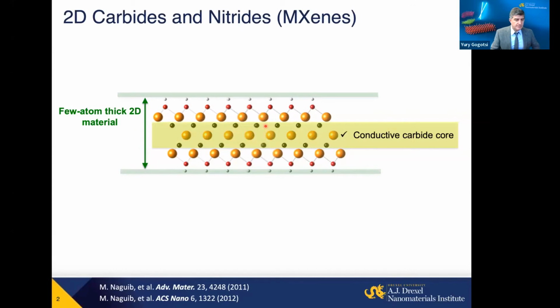What is unusual about those materials? The majority of them are metallic materials with a high density of states at the Fermi level, a high concentration of carriers. They have a conducting carbide and nitride core. But their surface looks like a surface of a transition metal oxide, hydroxide, chalcogenide, or halogenide, depending on what surface termination you have. So they combine properties of metals and non-metals, and this by itself is quite unusual, quite uncommon.